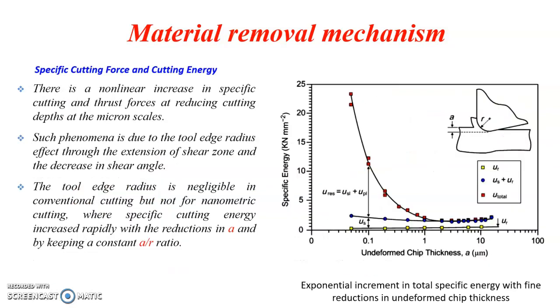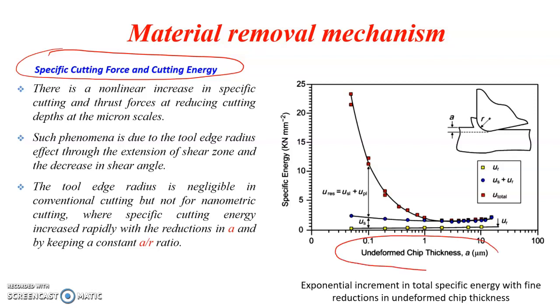In continuation with the tool edge radius effect, we will discuss the specific cutting force and cutting energy in diamond turning. As discussed earlier, with the reduction in undeformed chip thickness to the levels of micrometers or nanometers, we can see an exponential increase in the specific cutting energy, and this is mainly because of extension of the shear zone and the decrease in shear angle.